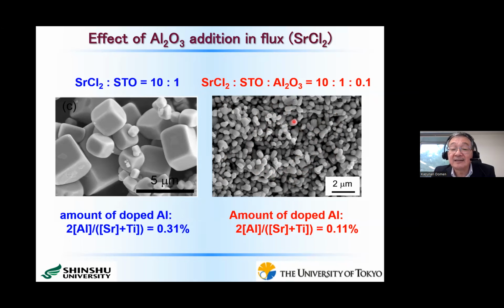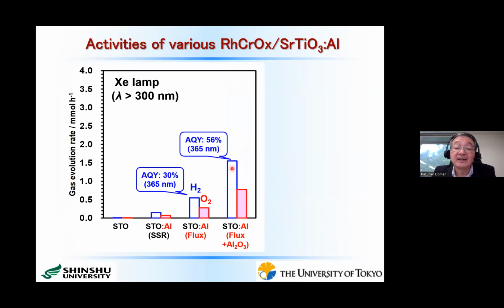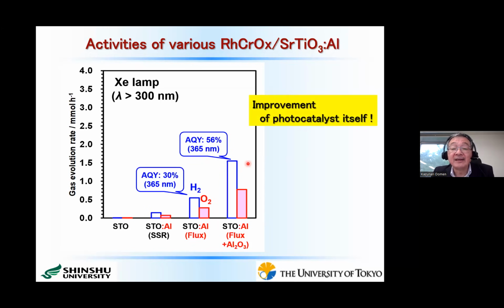So this is the reason that I said that this alumina seems to work as a shape controlling reagent. Then we use this small size of aluminum doped strontium titanate. Then we can get, in this case, an apparent quantum yield that exceeded 50%. So this is a very good quantum efficiency for overall water splitting reaction at this wavelength region. But so far, what we did is improve the property of the strontium titanate itself, so we have just focused our effort on the improvement of the photocatalyst itself.